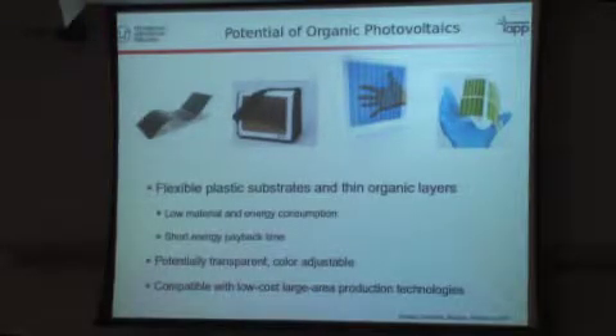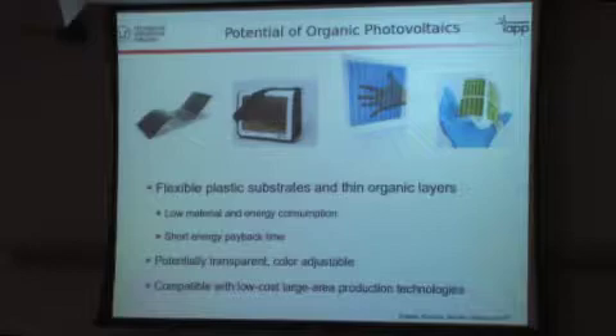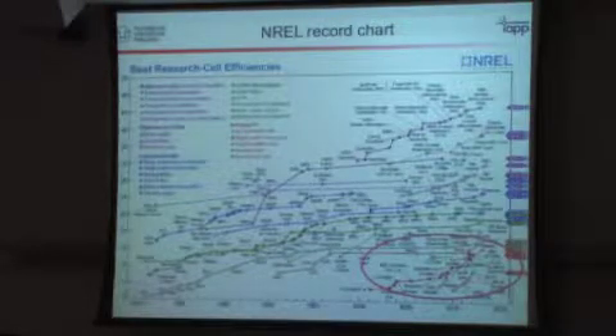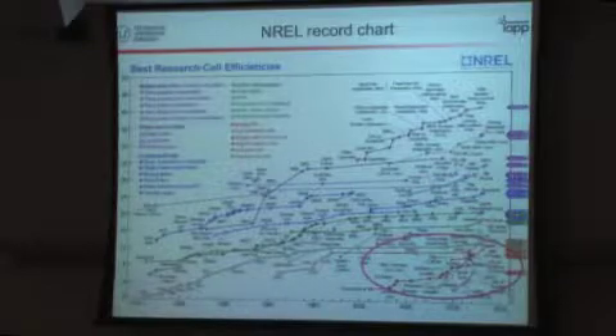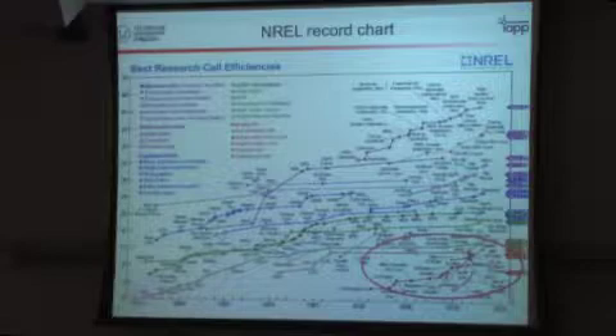Unfortunately, most of these potential points are not really realized, and for several reasons, we still have to work a lot to really meet the expectation. The one issue with this organic PV is that when you look at this NREL plot of the efficiency of photovoltaic systems, the organics is still down here in the noise, so to speak. As you can see, there's a large gradient, but still we are in the 10% range with efficiencies. And the established photovoltaic technologies are in the laboratory at least well above 20%.